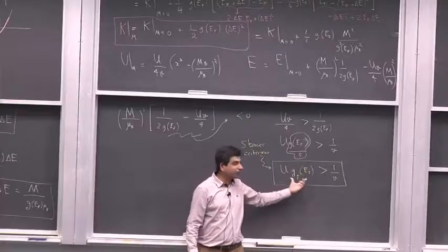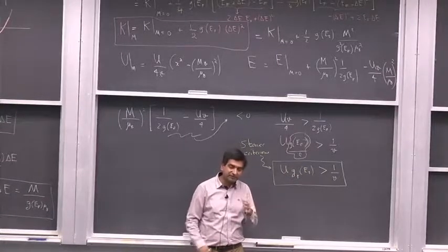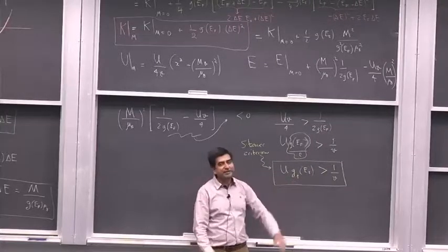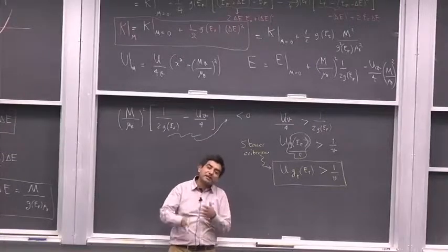Now both of these terms can be calculated through simulations, through DFT, density functional theory, and I'll show you some results today. So this is the Stoner criterion, and this tells us that if this condition is satisfied, the sample would like to magnetize spontaneously.